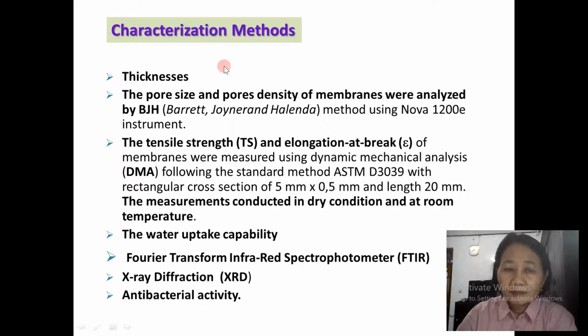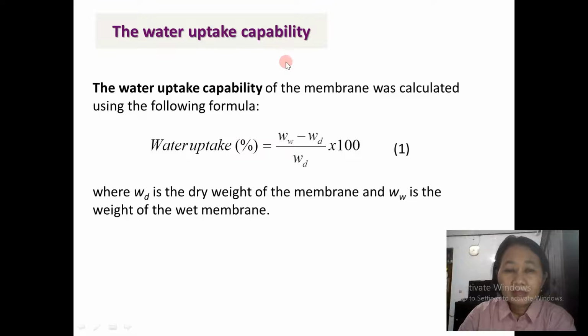Characterization method. For this research, we have measured the thickness of the membranes, and also the pore size and the pore density of the membranes by using the Barrett-Joyner-Halenda method. We have also measured the tensile strength and elongation at break by using dynamic mechanical analysis. And then we have measured the water uptake capability, Fourier transform infrared spectrophotometry, X-ray diffraction, and also done the antibacterial activity. For the water uptake capability, we have used Formula 1 to measure the water uptake of each membrane.